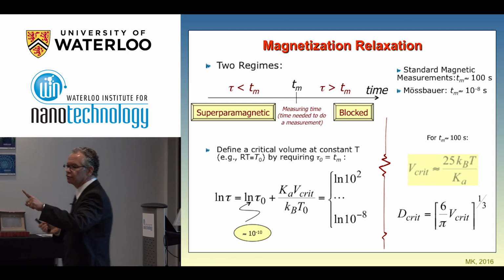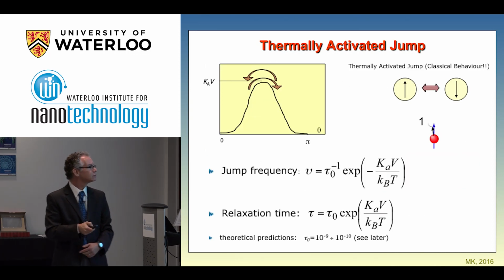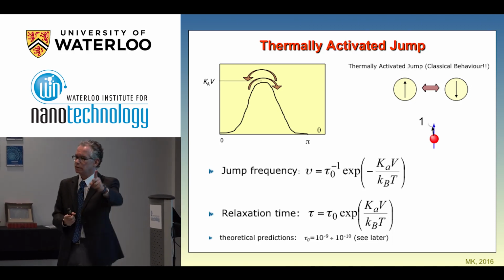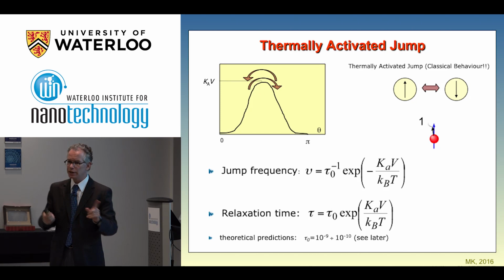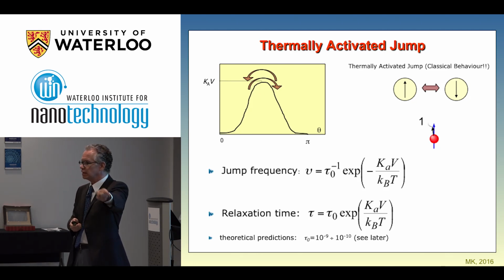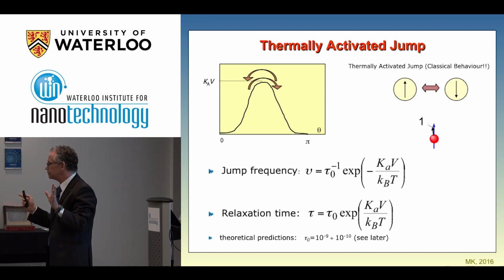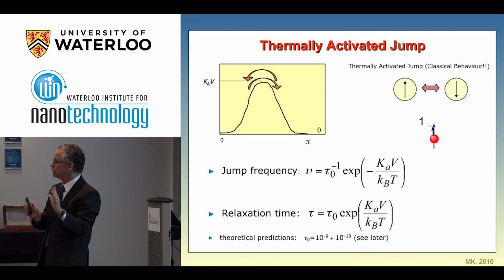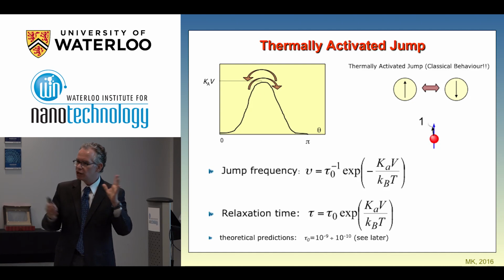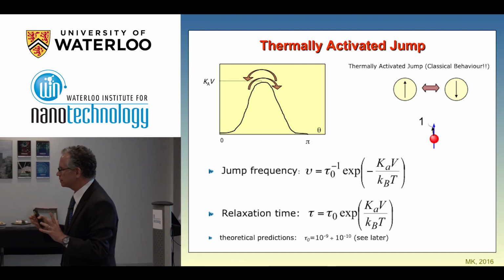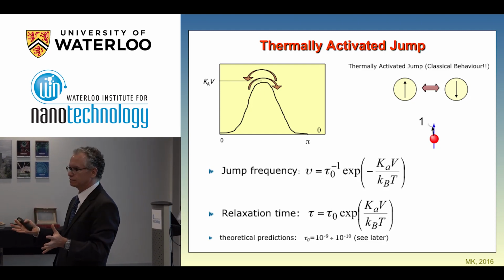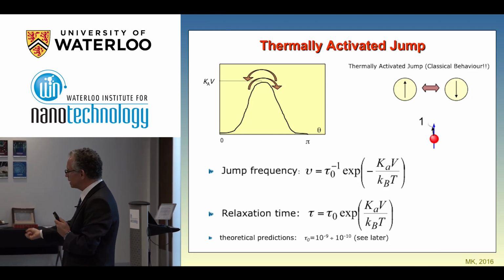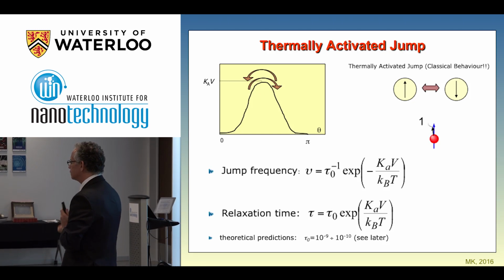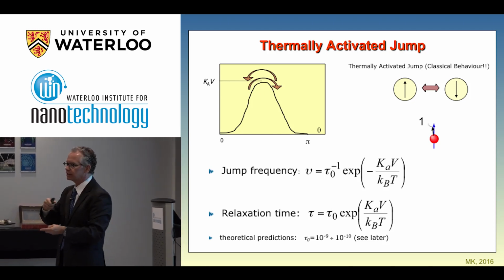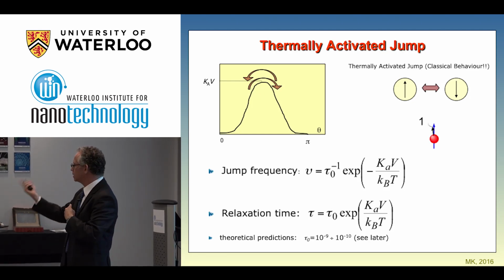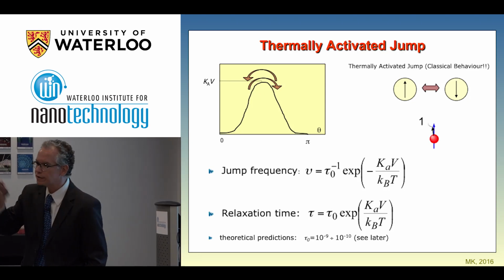If you wait long enough, if you have a nanoparticle, let me come back here a little bit. If you have a nanoparticle which is big enough, you have a jump frequency, and eventually this particle will stay there for years, and then eventually can jump to the other direction. There is a probability, which is not zero, that this will happen. It's extremely small, but it can happen. So even huge nanoparticles, let's say, just one extreme example would be our planet, the planet Earth, eventually the magnetic moment of the planet jumps from one direction to the other. You know that what is North Pole today was already South Pole, and it changed several times over thousands and thousands of years.